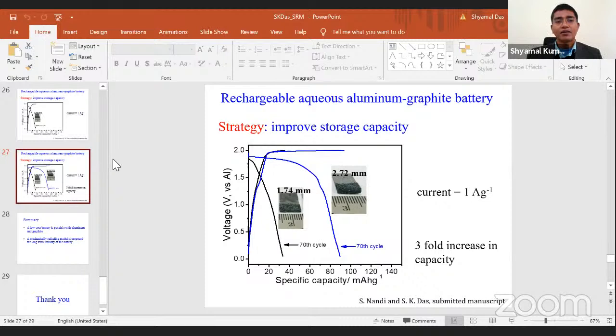We used lower current also, but when you use lower current, since we are working with a water-based electrolyte, there are other problems. Using lower current means we are applying an electric field for a longer period of time, and water may dissociate into hydrogen or oxygen if we keep it for a longer period. So there are technical disadvantages: this kind of cell may not be usable at low current rates. We have to go for high current rates only.